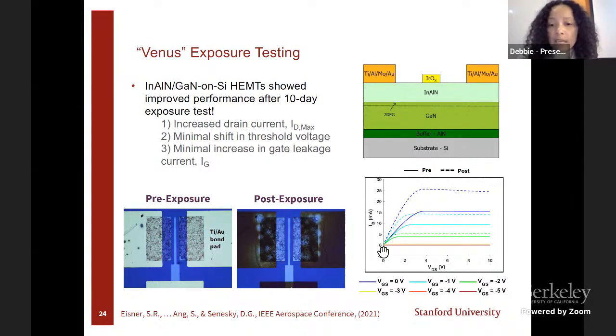What we're seeing in the IV response is actually an increase in the drain current. And so we're trying to understand what are the carriers in the iridium oxide after exposure to supercritical CO2. So this is ongoing work, but nonetheless, these transistors actually work better after 10 days in supercritical CO2, and a lot of studying threshold voltage, pre and post. And then, as I mentioned, we just did our in situ test as well.